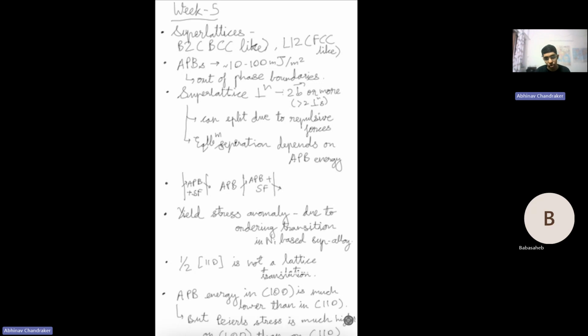Because you have two or more different element atoms in a superlattice or ordered phase, it is less favorable if elements of the same type come together. Elements of two different types together, for example AB, have a lower energy than AA, which corresponds to like elements coming together. Sir has shown this in his video. In case AA is coming together, the energy will increase, and that kind of boundary is called the antiphase boundary, where AA is forming, and the energy is almost equivalent to that of stacking faults. So this is also a kind of fault only, because locally there's a boundary getting created which has a higher energy.